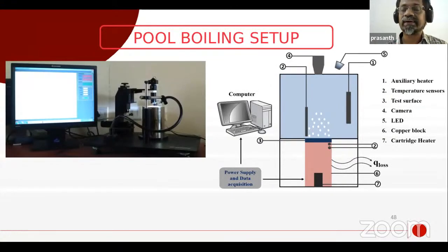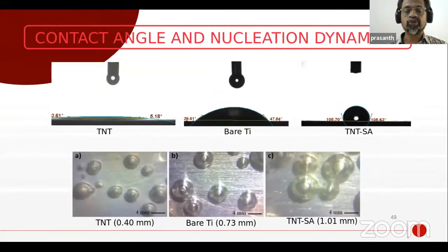Then in such structures, you can study the heat transfer mechanism by making a pool boiling system. That shows that in a TNT tubular structure, you can see more uniform nucleated bubbling compared to a stearic acid treated surface, where it makes a highly hydrophobic surface. And the bubbling mechanism, the bubbling frequency, I will show you the